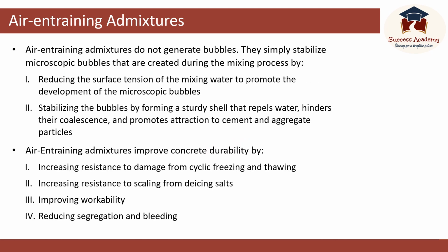Now let's see how these air-entraining admixtures work. Air-entraining admixtures do not generate bubbles. They simply stabilize microscopic bubbles that are created during the mixing process. They reduce the surface tension of mixing water to promote the development of microscopic bubbles, and they also stabilize the bubbles by forming a sturdy shell that repels water, hinders their coalescence, and promotes attraction to the cement and aggregate